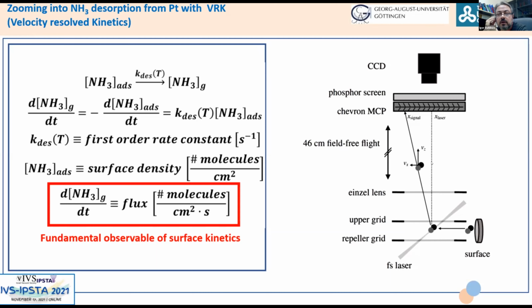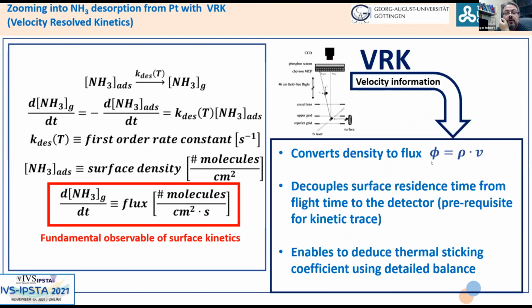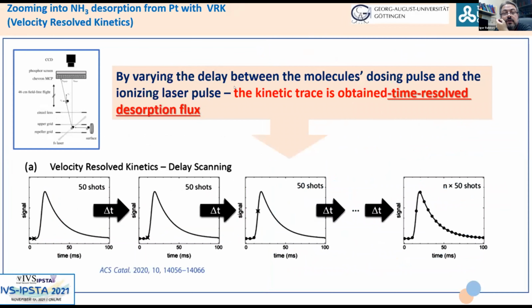Now they hit this detector, this MCP detector, followed by a phosphor screen and CCD, which overall can be taken as an ion camera, at a position which is proportional to their velocity in the direction perpendicular to the surface. So by recording an ion image, we can actually record velocity or even velocity distribution. This provides us a great deal of information because, having velocity, we can convert the density that we detect to a flux. We can furthermore decouple surface residence time from flight time to the detector, which is a prerequisite to having a reliable kinetic trace. And once we have the velocity distribution, we can deduce the thermal sticking coefficient using the principle of detailed balance. Now, if we vary the delay between the molecular dosing pulse and the ionizing laser pulse, we can detect a kinetic trace, which is the time-resolved desorption flux.